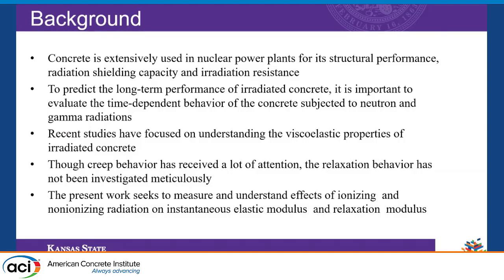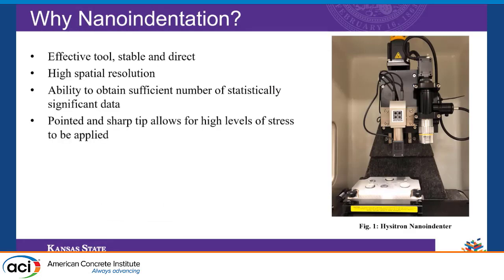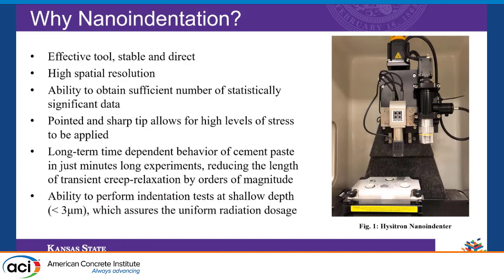Considering the scant data available on the relaxation behavior particularly, the present study seeks to measure and understand the effects of ionizing as well as non-ionizing radiations on the instantaneous elastic modulus and the relaxation modulus. Nano indentation is a very effective and direct tool with outstanding stability, which allows us to hold the load and depth signal for a very long time. You can obtain a very large set of statistically significant data conveniently. The major advantage is the ability to perform the test at very shallow depths — less than 3 micrometers — ensuring that we are indenting in the location where we have uniform dosage of the radiations.